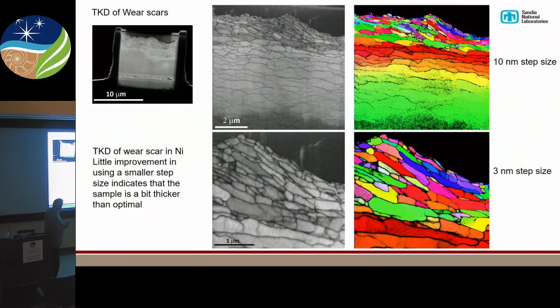And over here we have our TKD maps. This was at 10 nanometer step size. We get some very nice work. This is at 3 nanometer. And now you get an idea that you can actually see within a few nanometers the grain size. You resolve a lot of the information within here that we couldn't get with normal bulk samples because of the size of the interaction volume and the size of the electron beam. So we're really starting to push this to very, very low, or high, resolutions, if you will.